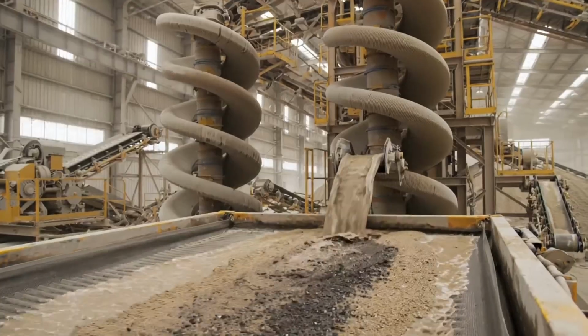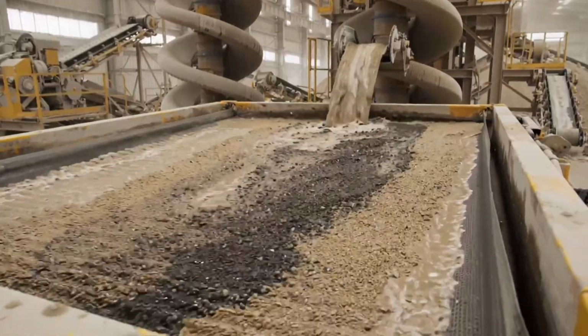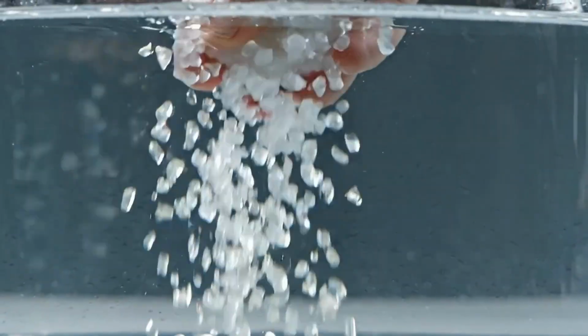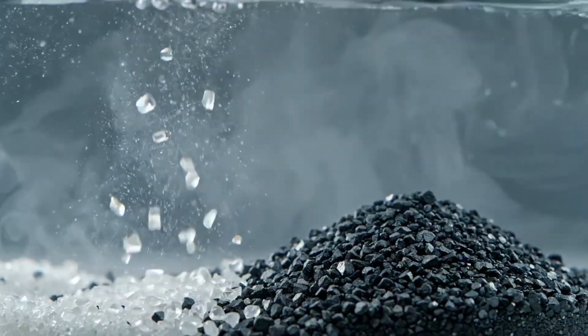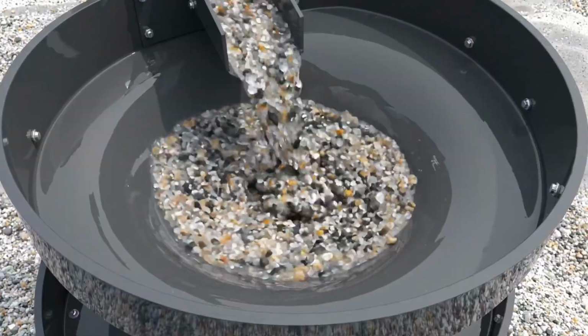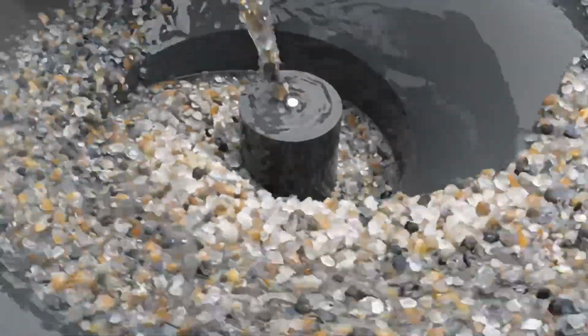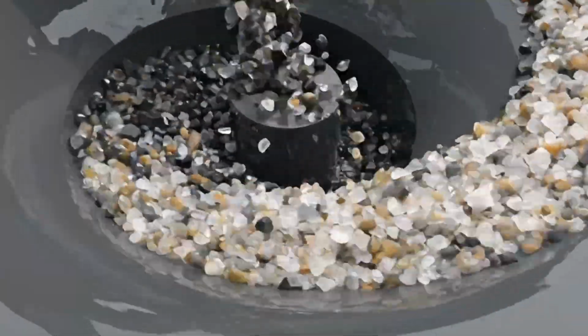Titanium minerals are denser than quartz sand. When the mixture is moved with water through spiral channels, the heavier grains tend to settle to a different area than the lighter grains. This results in a much richer mineral concentrate, while the discarded sand is either returned to the system or managed as controlled waste.